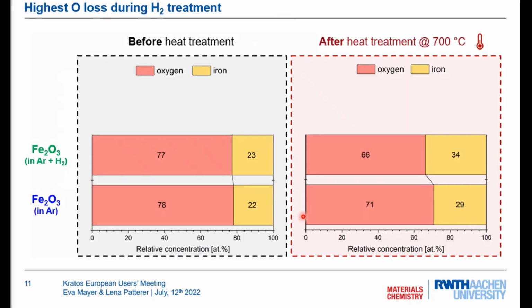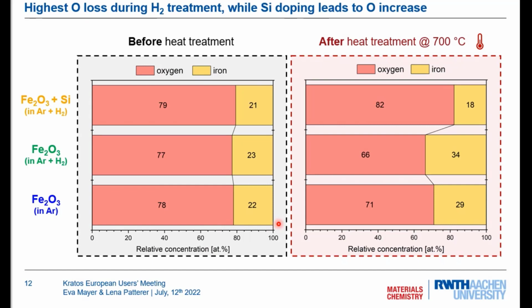But first, let me show you the chemical composition that was determined by the survey spectra from the XPS data. And here we have in red the oxygen content and in yellow the iron content. As you can see beforehand, both samples were very similar. And afterwards, the sample that was heated up in argon has a lower iron content compared to the one that was heated in argon plus hydrogen. And here, for comparison, the one containing silicon.